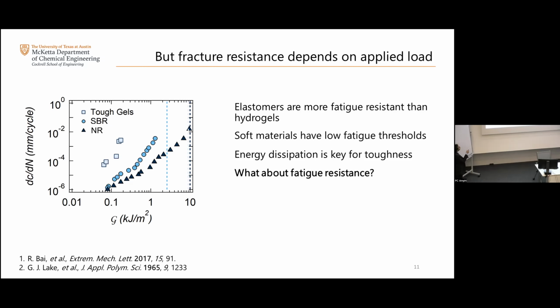These are tough gels developed by Zhigang Suo's lab at Harvard. And the fracture toughness of these systems under very specific conditions are very similar to those of natural rubber. This is what I'm indicating with this dashed line. But the fatigue behavior is very, very poor compared to that of natural rubber. So natural rubber is right here. So effectively what you see is that you can have two systems that have, under very specific conditions, very similar toughness, but they have very different fatigue resistance.